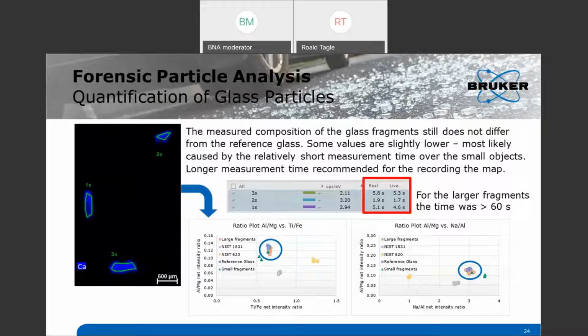And if you compare, for example, the element ratios, and element ratio comparison is more reliable for small particles and is also what is recommended in the ASTM norm, you see that the objects, especially the large fragments, represent the composition of my reference sample very well, whereas the small fragments, some of them you see as triangles, are a little bit farther away from my area of interest. So the small particles are not reliable for this identification, and the main problem is that the measurement time is not sufficient. Basically, the validation in this case fails because the time is too short.